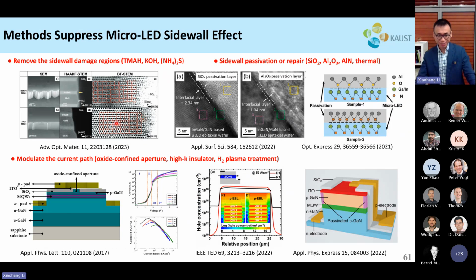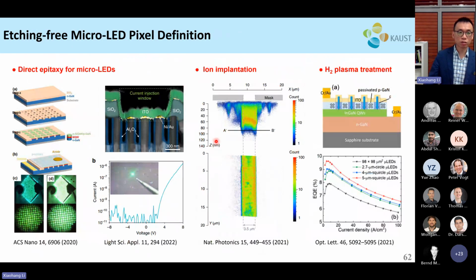So how do you address it? Many groups have proposed different techniques. Some use chemical etching to remove the amorphous layer. Some utilize oxide passivation by ALD, and people have also utilized more sophisticated techniques, right? Such as controlling the current path so that the current does not flow to the sidewall, right? And also different studies have proposed the use of etch-free techniques, right?